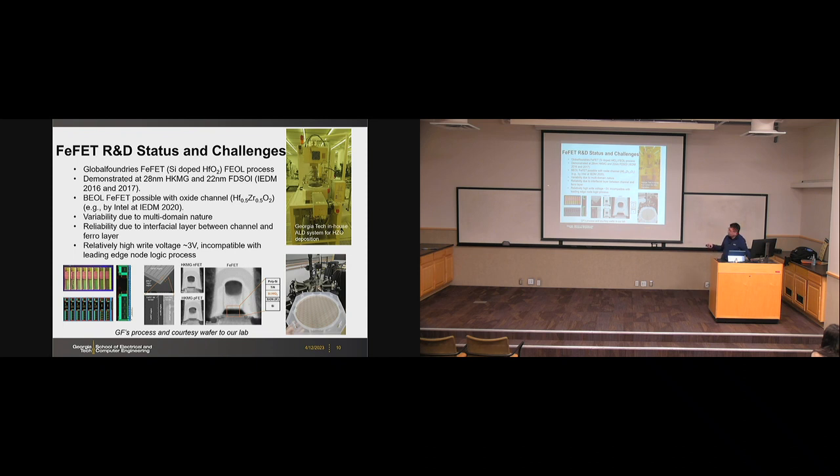And also the write voltage is still a little high, like 3 volts. This is incompatible with the leading edge logic process. For example, at 7 nanometer, 5 nanometer, the VDD is about 0.7 volts. So anyway, here I show some images from GlobalFoundries. Because we have active collaboration with GlobalFoundries, they ship their 12-inch wafers to our lab for characterization. So we have access to their latest technology. And also, at Georgia Tech, we set up our in-house ALD system for growing the hafnium zirconium oxide to have our in-house samples as well.